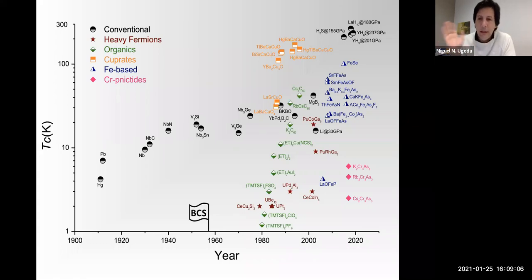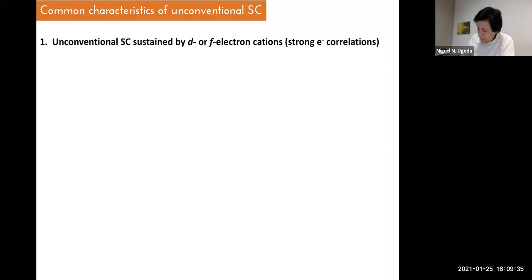So nowadays, unconventional superconductivity is basically not the exception, but the usual case, and the conventional superconductors are basically the exception. So there are many different families of unconventional superconductors, with quite diverse superconducting properties. And actually, there is no theory that explains this behavior at once, no unified theory. However, there are certain common characteristics of these unconventional superconductors. One of them is that in general, and only in general, there are exceptions to this one as well, unconventional superconductivity is sustained by d or f electron cations. And therefore, these electrons are well known to lead to strong electronic correlations in the material.